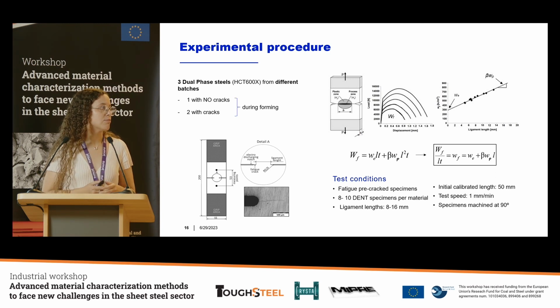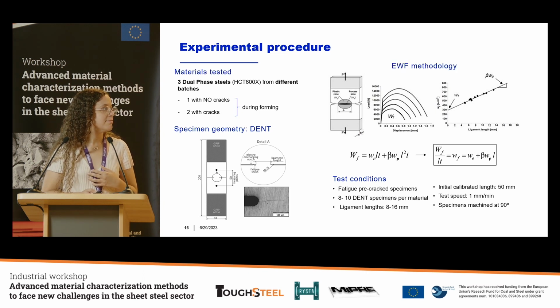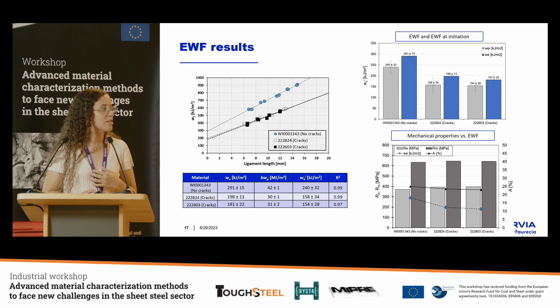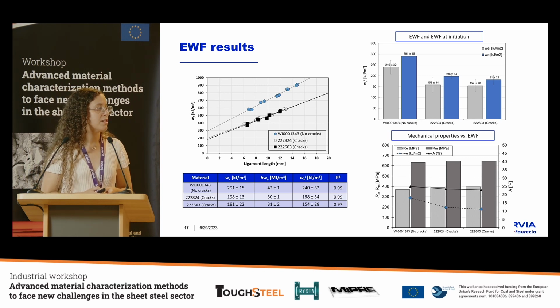Here we can see the test conditions we used to perform the test, which used fatigue pre-cracked specimens, about 10 specimens for each material, and the ligament length from 8 to 16 millimeters. Okay. Next on, we can see the results that we got from these 3 materials that we tested. And we can already see some huge differences for the material presenting no cracks in the forming process, which is the first one we can see. And then we can find lower fracture behavior for the other 2 materials that presented cracks during forming.